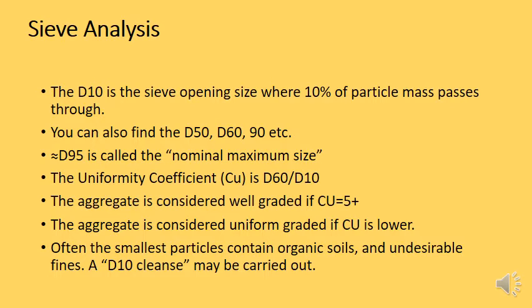The D60, 60% of the aggregate is smaller than this diameter, 40% is greater. Now, the D95, or the 95 percentile diameter, is called the nominal maximum size. We can't go through the aggregate and look at every single particle and find what is the biggest size. So the D95 gives us an idea of the nominal maximum size from our sample.